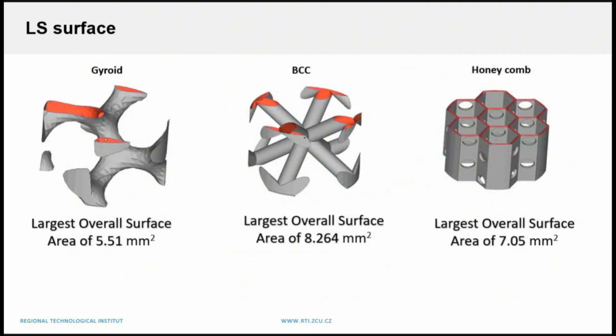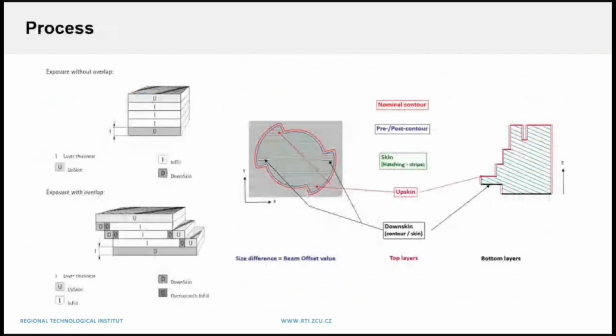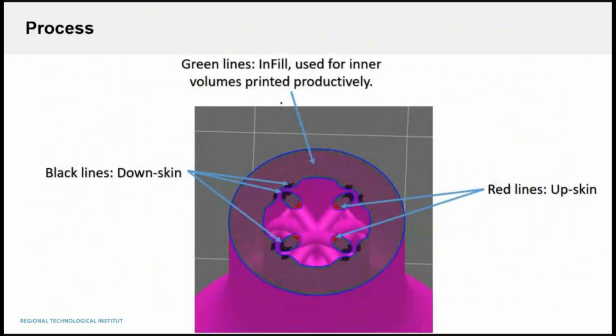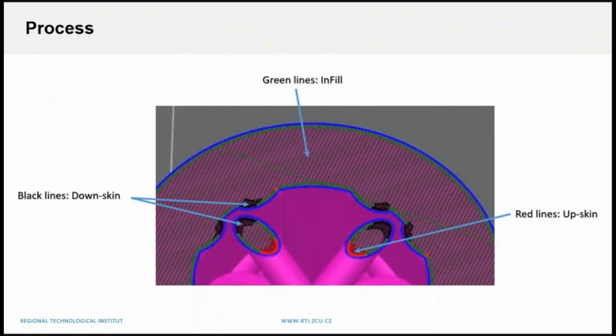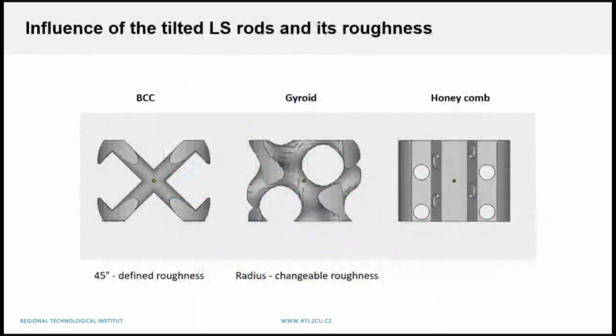And in this case, when this area is connected to the shell of the body, there are a lot of concentrators of potential defects. And generally, this is the trouble because of the downskin in this area. When we check the process, here you could see that the rods are connected together. A lot of downskins are used. This is a nice potential for internal defects, and this is why all the cracks are created in this area of the connection of the lattice structure.